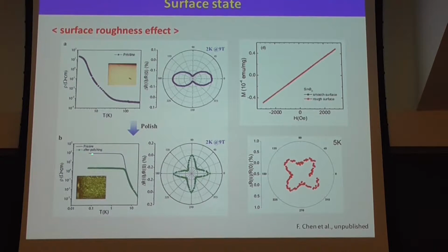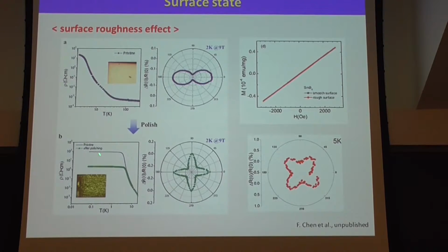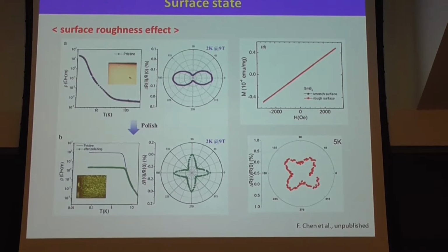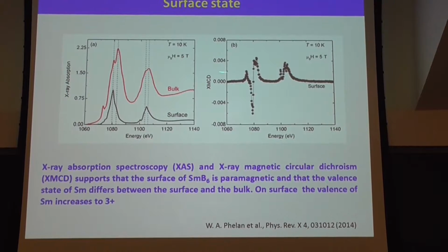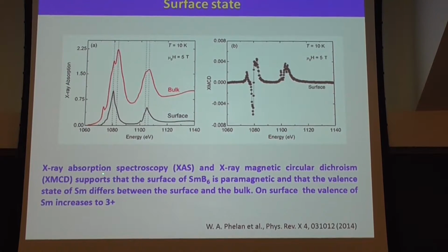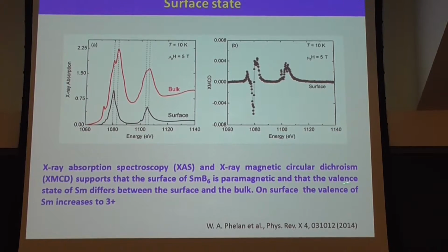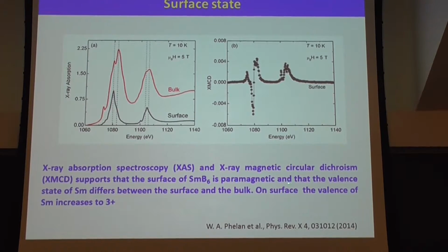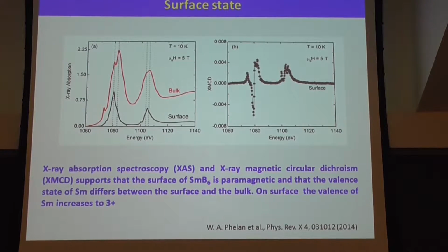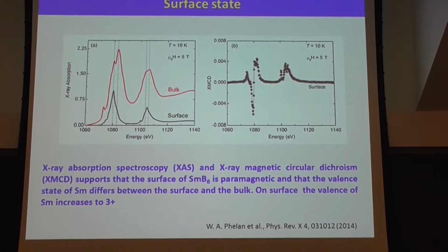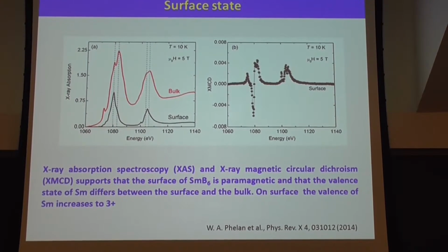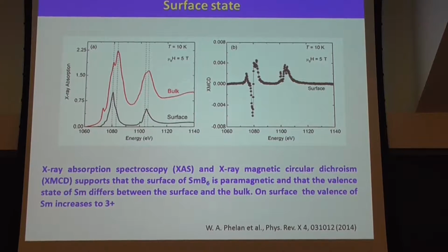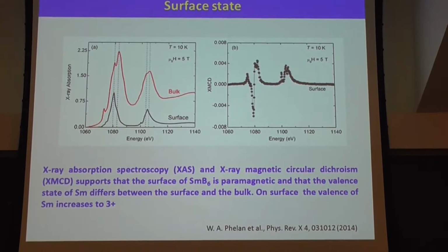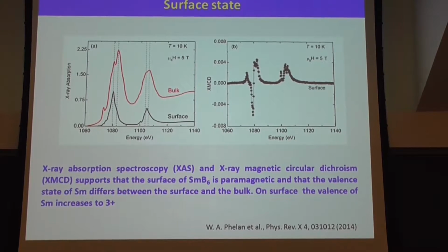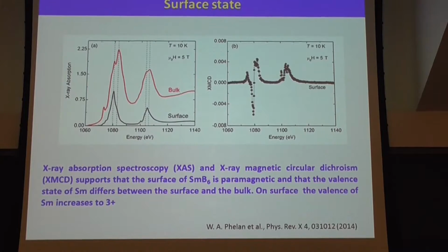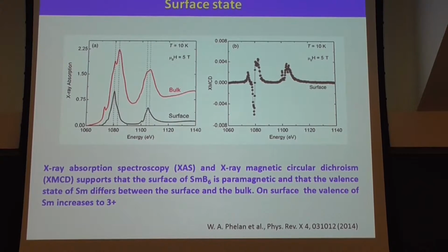You can see it also changes the surface conductance, you know. This is orders of magnitude changed just by roughness. And also for the surface, standard X-ray absorption spectroscopy and X-ray magnetic measurements support that the surface state is paramagnetic. The valence is different in some areas of the surface, but maybe this changes the surface conductivity, and the anisotropic phase symmetry is also maybe due to the valence change, we think.